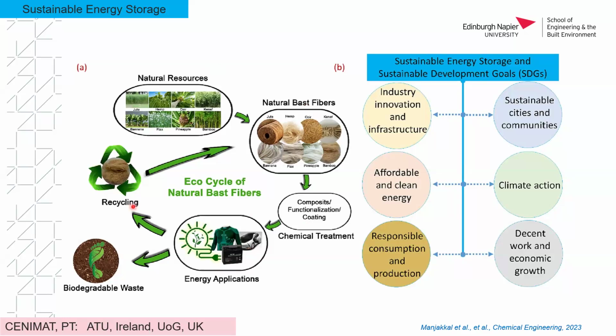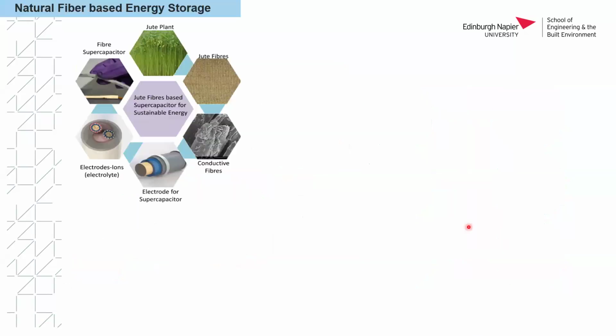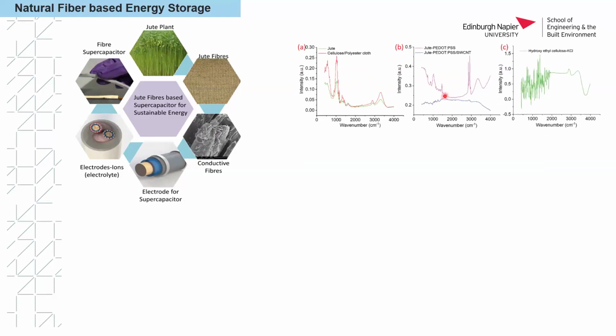2D material coating on top of these fibers. Okay, I can show you one example. In one of my works, there is a jute fiber. That jute fiber I converted to a conductive fiber. Then using that conductive fiber, I developed a new electrode, where the conductive fiber was coated with PEDOT:PSS and also carbon nanotubes. You can see here it's like a cable-type electrochemical capacitor. As you can see here, that's a single cable. And this is actually the converted jute. And here you can see the FTIR spectrum of this material as well.